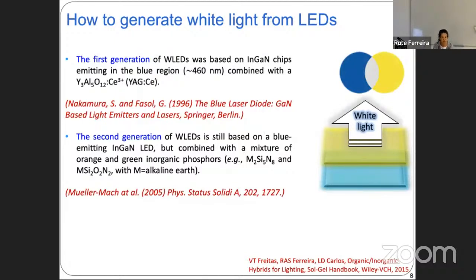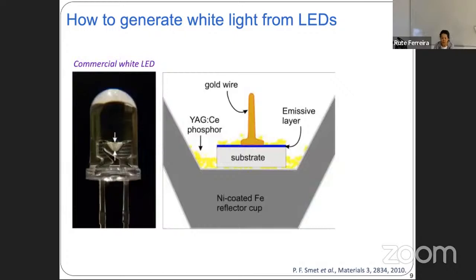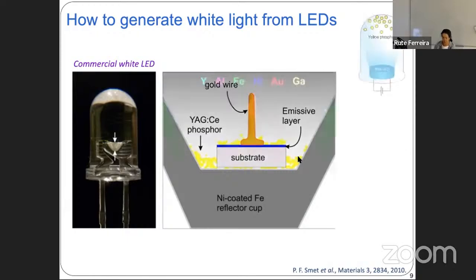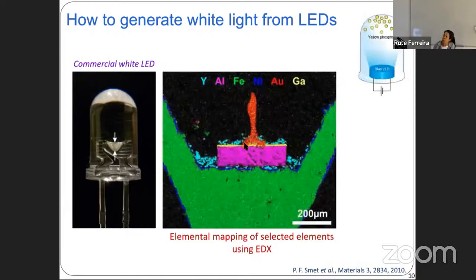The second generation is still based on a blue emitting LED, but combined with a mixture of orange and green inorganic phosphors. This first generation, and it's just by curiosity, is a photograph of the current white LED, where you can see the emissive layer, the blue emitting layer that is coated or covered with the cerium phosphor. And also just for you to note a little bit about the chemical content of the LED, you can see an elemental mapping of some other elements also present in the current LED.